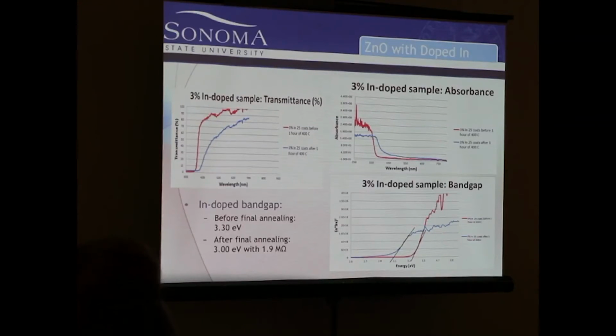And so after we annealed it, we got it down to 3.0 electron volts with a resistance of 1.9 megaohms, which is still too high. We want it in the ohms or kiloohms area, but we did get a final resistance on the surface and we got the band gap down. So we were really able to see that indium does shorten the band gap.